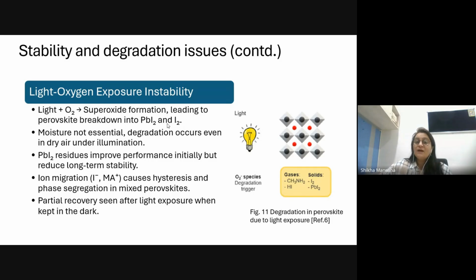In the previous case we saw that if there is moisture but no light, there is still degradation. But here, even if there is light and no moisture, there is also degradation. As a byproduct we have lead iodide as residue, lying on the material surface itself. If there is a little bit of residue, that's not a problem, but over time, if this residue increases, it will have some impact on our device performance. So this is something that needs to be taken care of.